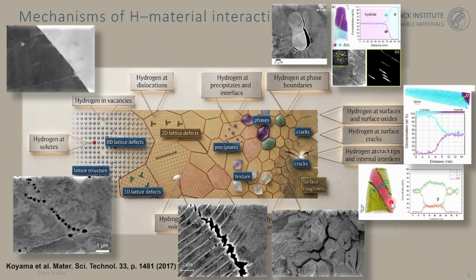Here you have an example from atom probe tomography, where you see the formation of hydrides, for instance, and likewise here and here. And here you again have a classical decohesion phenomenon in a nickel-based superalloy. With that, I stop here and hope that these few slides make you sensitive to how you should discuss the individual mechanisms and their interplay in the field of hydrogen embrittlement.